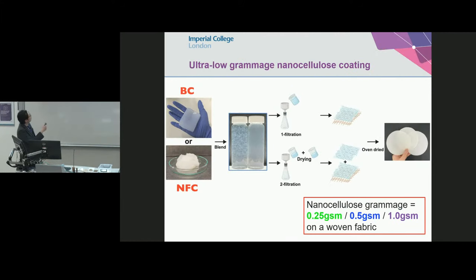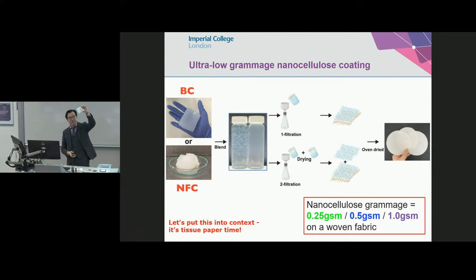So we started with a bacterial cellulose or wood-derived nanofibrillated cellulose. You filter this thing, you coat this thing onto the fabric themselves. So what we actually did achieve was the different grammages, essentially how much mass per unit area. So we go up to 1 GSM, your writing paper is 70, 80 GSM. Your Imperial College tissue paper, it's 15 GSM. So we're coating 15 times less of this material on a piece of open woven fabric.